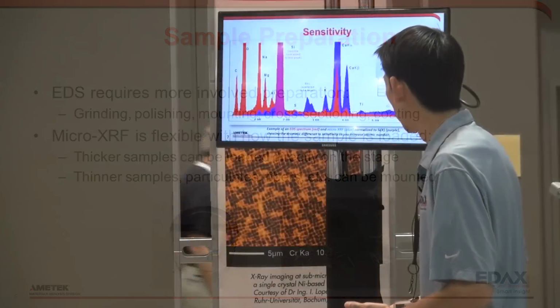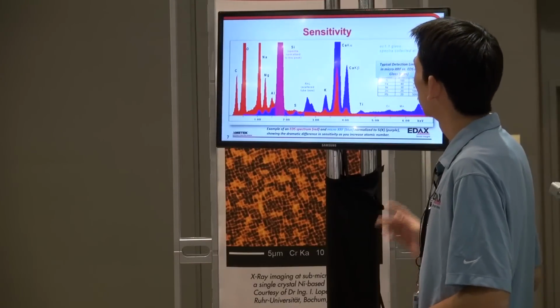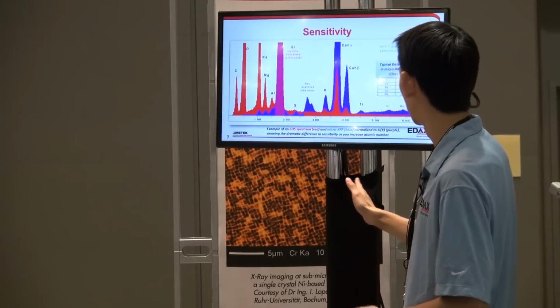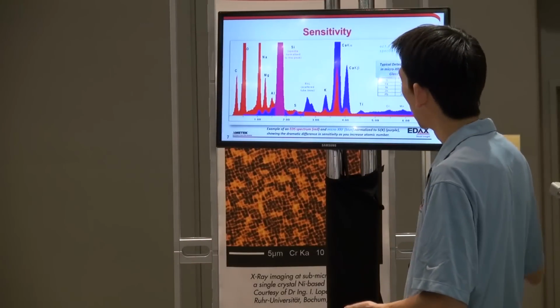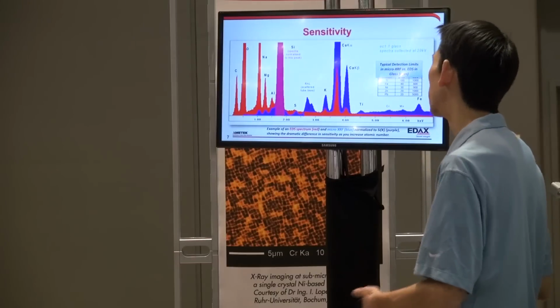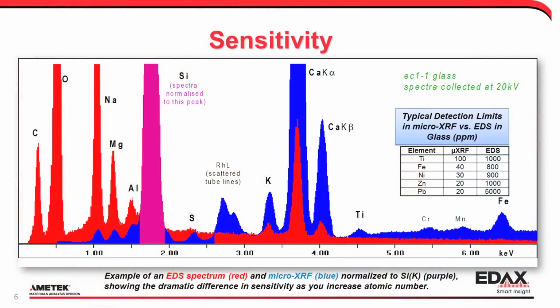Another thing that's been mentioned is the sensitivity. The sensitivity from micro-XRF, as you can see, leans heavily towards the higher energy elements, and EDS leans heavier towards better performance for the lighter elements. Here we have a glass standard that we collected at 20 kV for both techniques, and you can just see the spectrum overlay. The silicon peak is where they were both normalized, so that's purple. But the red spectrum that you see is the EDS, and the blue spectrum is the micro-XRF.